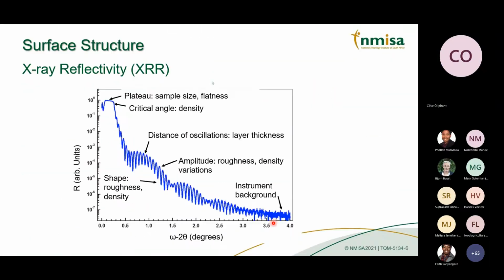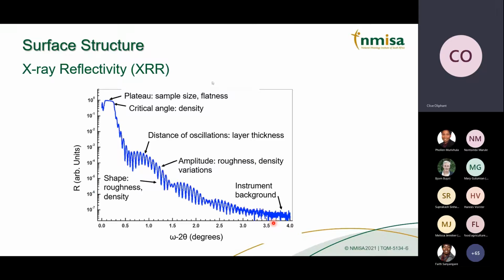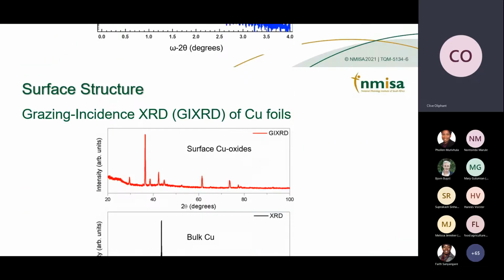Then we also have another technique called X-ray reflectivity, XRR. This is one of those techniques that can give you a wealth of information for thin films and coatings, which is quite relevant for many industries. If your material is below a few hundred nanometers or so, you can get your roughness, your density, or interfacial roughness. So microelectronics device performance can be monitored, or it can be extracted using this sort of technique. And I'll show you an example of it later on.